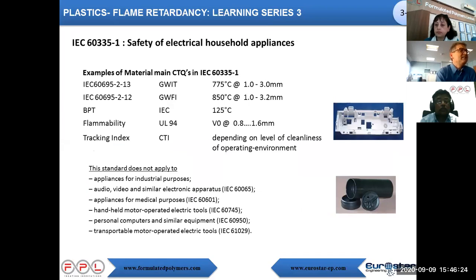So this IEC 60335 is really applied to household appliances, and it's where we have more requests, and it is the more stringent test. You need to pass the GWIT at 775. This is the ignition temperature. Flammability index 850. Ball pressure test, which is a kind of thermal measurement of material resistance. Flammability, as KK explained, most of the time V0 is needed at 0.8. Tracking index is more related to the electrical resistance of a material. Once more, this standard is very limited to household appliances, but nonetheless, people even in automotive are looking at this test, because for them it's sometimes more representative than UL for a failure, because in this case there is no open fire, there is an overheated component by an overload.